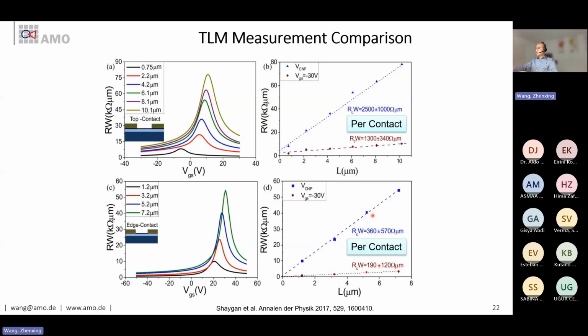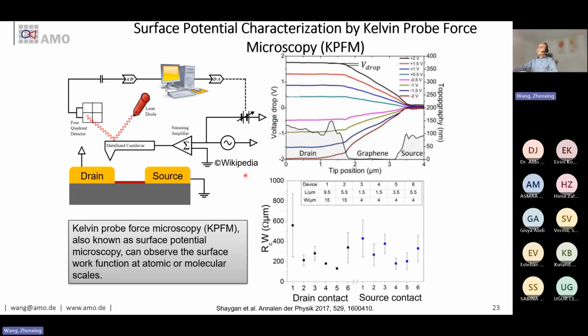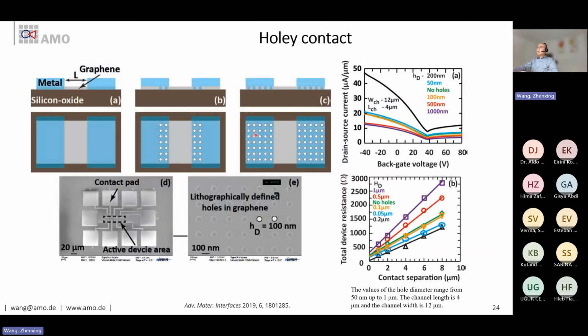Of course, these are two conditions. One is at the Dirac point, and this one is at the highly doped region. We confirm this contact resistance with KPFM, Kelvin probe force microscopy, to really measure this contact resistance, because you see there is really a potential drop at the interface which corresponds to the contact resistance. And then we also extract directly the contact resistance from here. Then we plot it here, and it is in the same range as the TLM method.